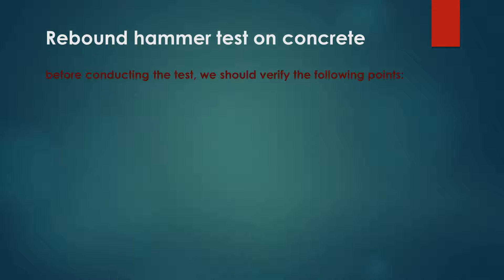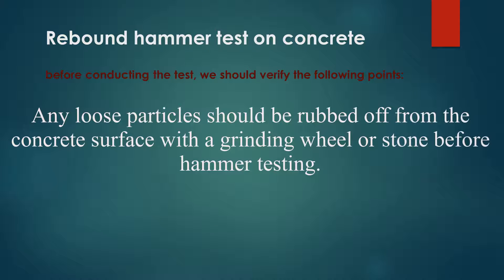Before conducting the test, we should verify the following points. The concrete surface should be smooth, clean, and dry. Any loose particles should be rubbed off from the concrete surface with a grinding wheel or stone before hammer testing.